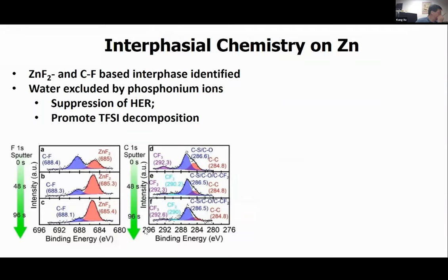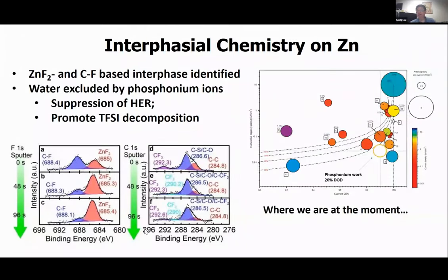And in order to promote this TFSI anion decomposition, the hydrogen evolution reaction from water has to be suppressed significantly. So the phosphonium ion plays a key role there in excluding water from the interface. So where are we right now for this work?